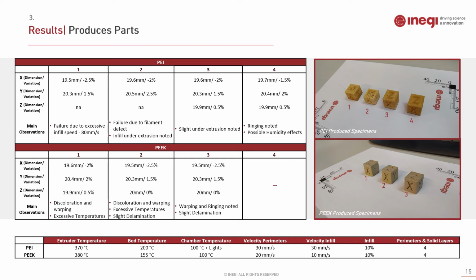The only defects noted were the presence of some ringing effect and some small zones with little discoloration, which we believe to be due to some humidity in the filament. We also had some consistent dimensional variation in the parts.